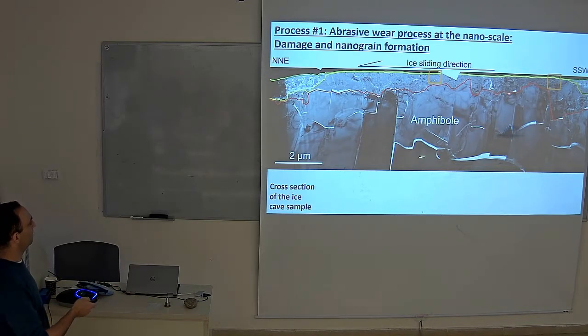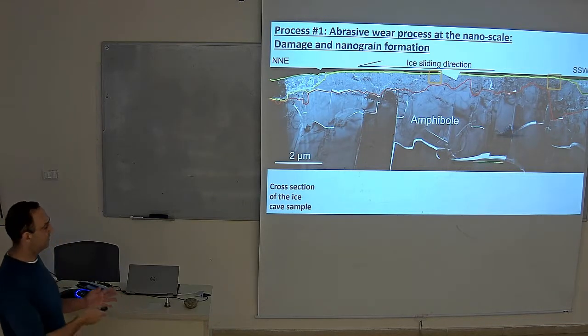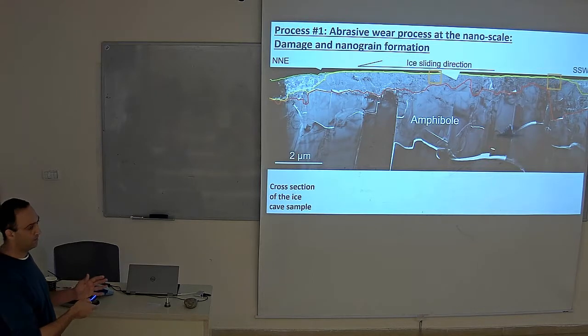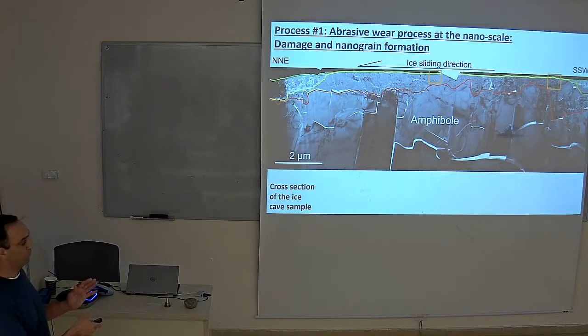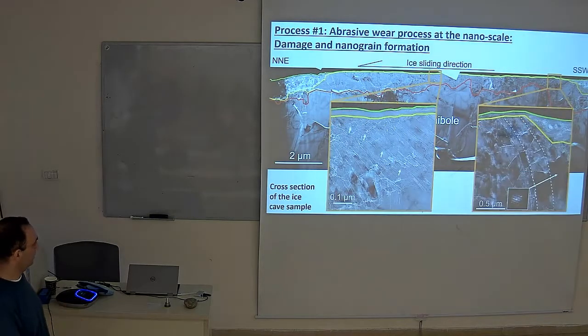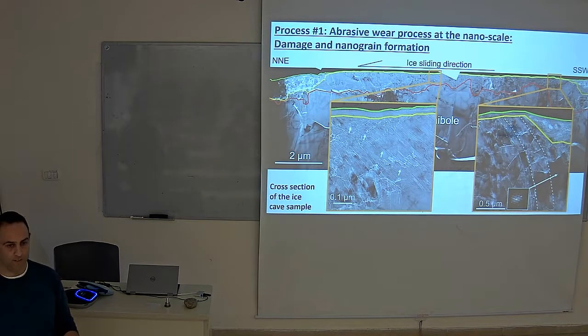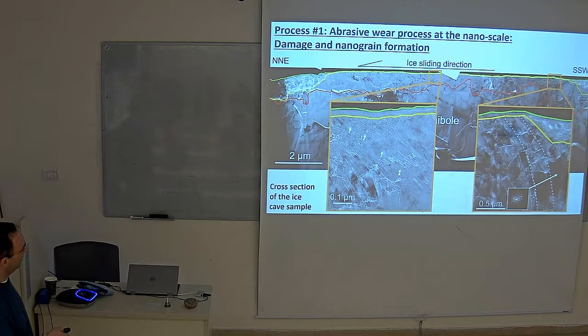And what we can see easily is that the amphibole crystal is very intact, besides some cleavage planes that cross it. And above the red line that I marked here, there is change. There is much more deformation in the amphibole crystal, and also there is a bend toward the ice sliding direction. So something like this. And let's zoom in. These are the cleavage planes, and they are bent toward the surface. The original structure of the lattice still exists by X-ray diffraction. We can see it's still the same amphibole, but rotated. And another important observation is that, following these arrows, there is a reduction of grain size toward the surface.